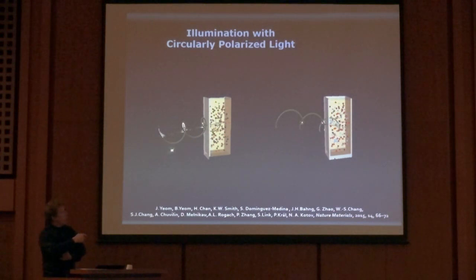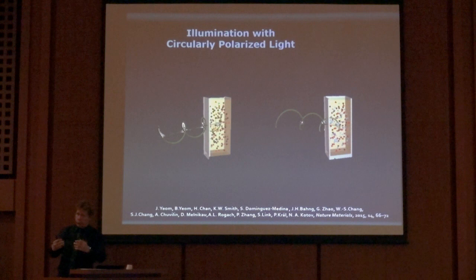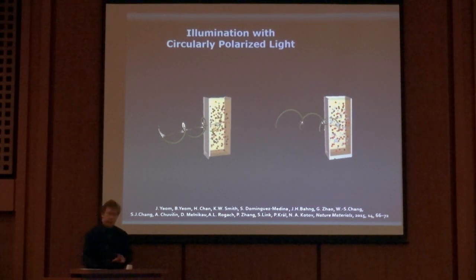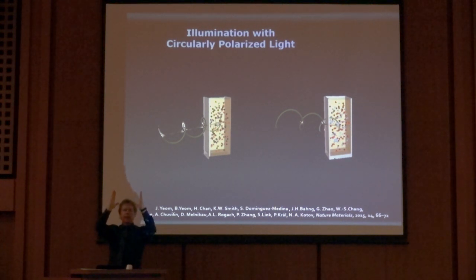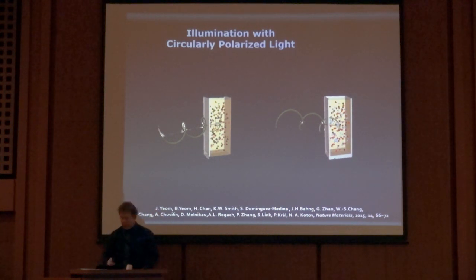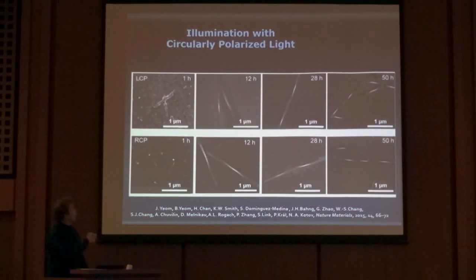And it was obtained. So we used here the racemic dispersion of thioglycolic acid stabilized cadmium telluride particles and illuminated it with left and right circularly polarized light. So what's happening here? The dispersion has no circular dichroism at all. It has chiral particles there, but the number of left and right particles is equal. We illuminate them with chiral photons, and as the result, we translate the chirality of the photons, left and right photons, into the chirality of the matter. So if we use left photons, we have the left twisted ribbons, right photons, the right twisted ribbons.